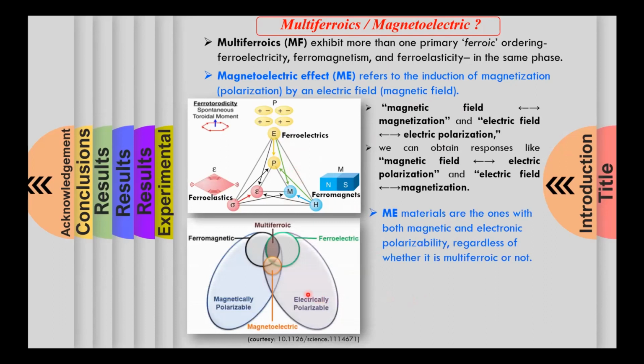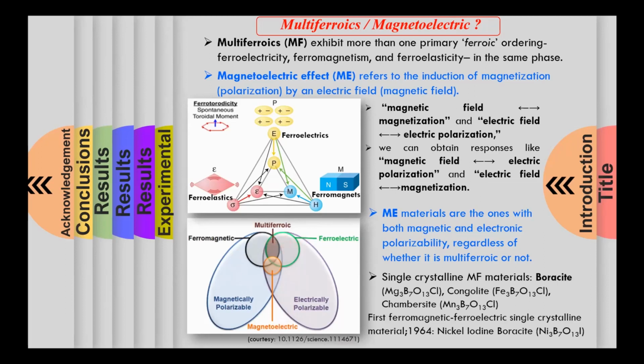Of course, we need to differentiate between a magnetoelectric and a multiferroic, because all magnetoelectric materials can have both magnetic polarizability as well as electrical polarizability, but they are not necessarily ferromagnetic or ferroelectric. So basically, not all magnetoelectric materials are ferroelectric multiferroics. Boracites were probably the first known multiferroic materials. In fact, a variety of boracite phases were realized to be either ferroelastic or ferromagnetic or ferroelectric. And the first ferromagnetic ferroelectric single crystalline material was nickel iodine boracite, which was discovered in 1964.